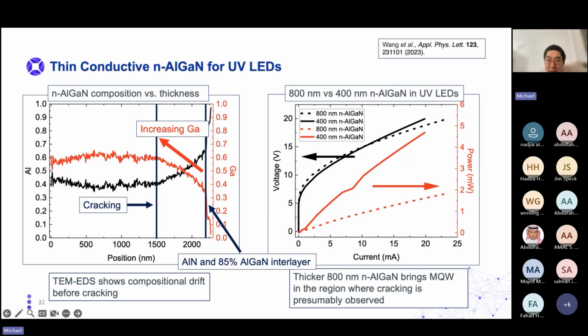So this is what occurs when you try to grow too thick. So basically what happens is we can't grow too thick, so we have to grow thin and very conductive. Otherwise, our current spreading is incredibly poor in our UV LEDs.